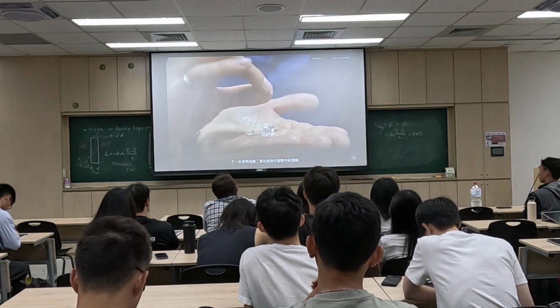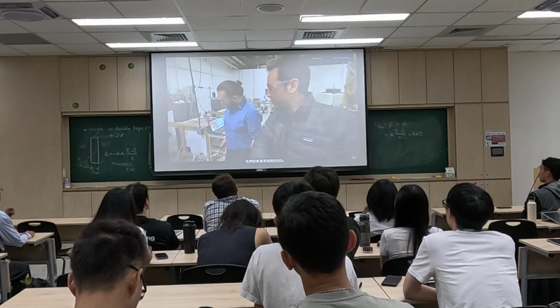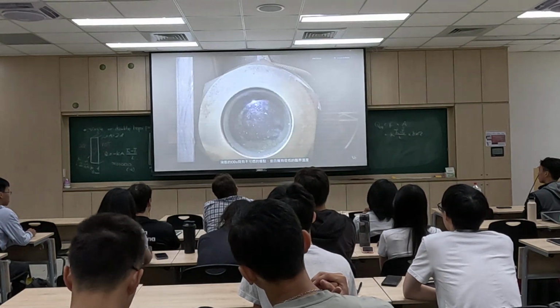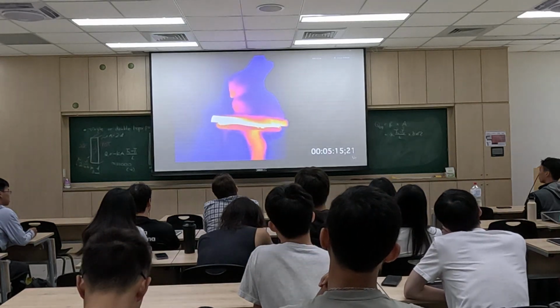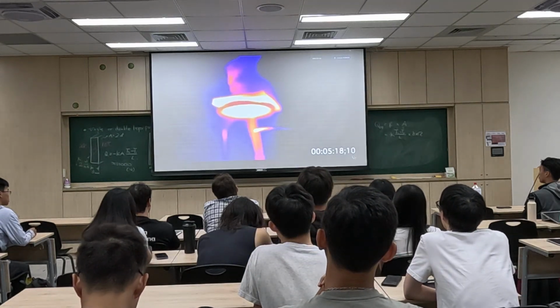The next step is to replace the alcohol in the gel with liquid carbon dioxide. We're about to see liquid CO2. The liquid CO2 has the advantage of being non-flammable, plus it's got a low critical temperature. Open up, and it's floating in. Yeah, it's floating in, there it goes. You can clearly see that it's so much cooler on top. I knew I was underwater, I just didn't realize I was this underwater.